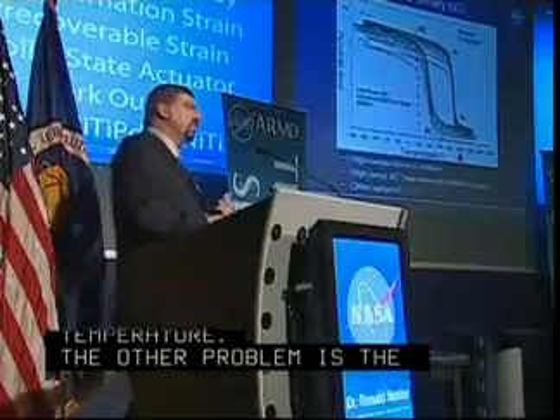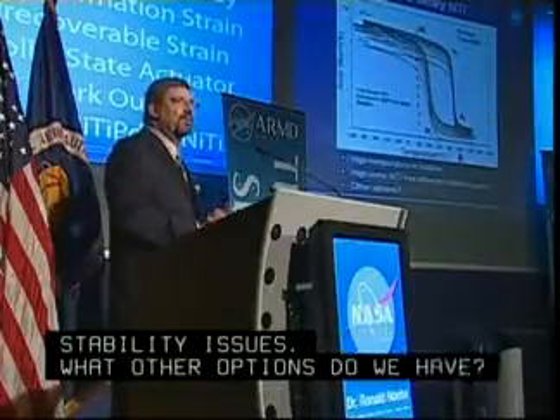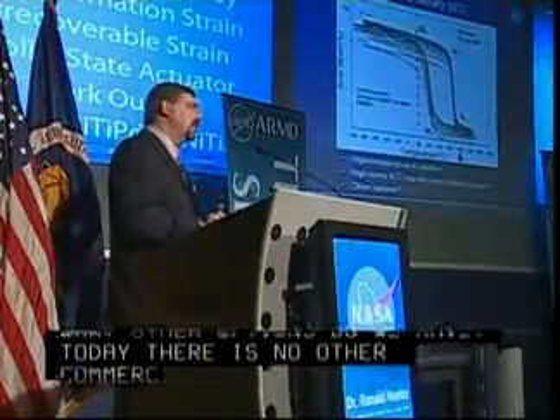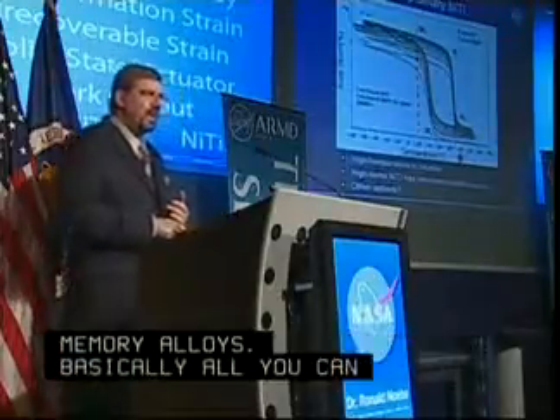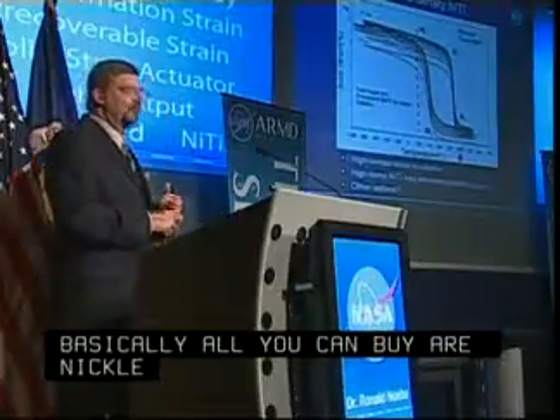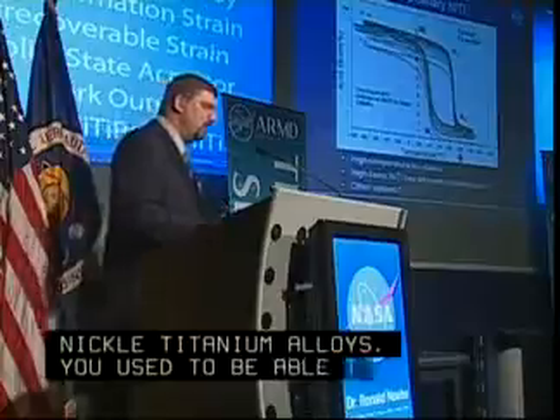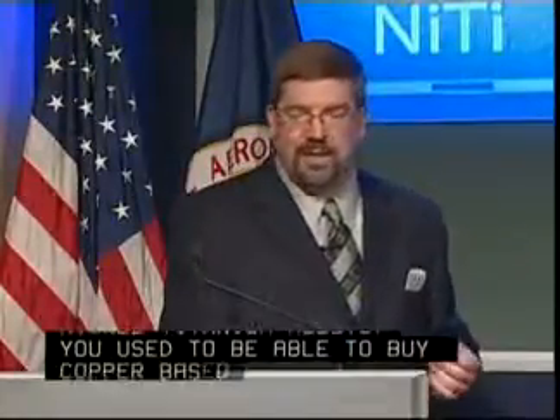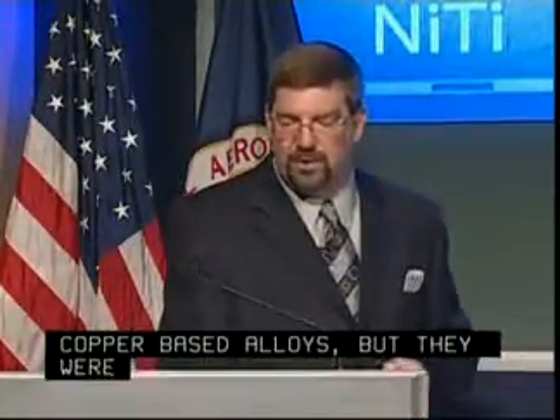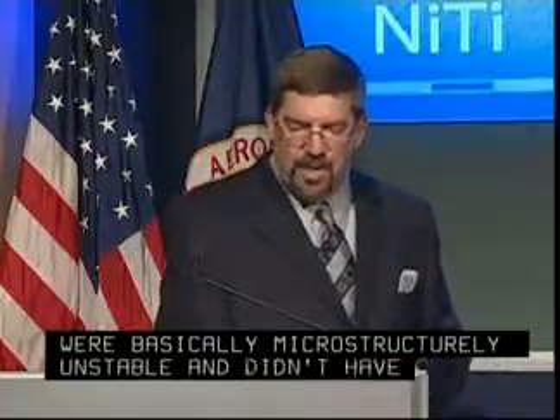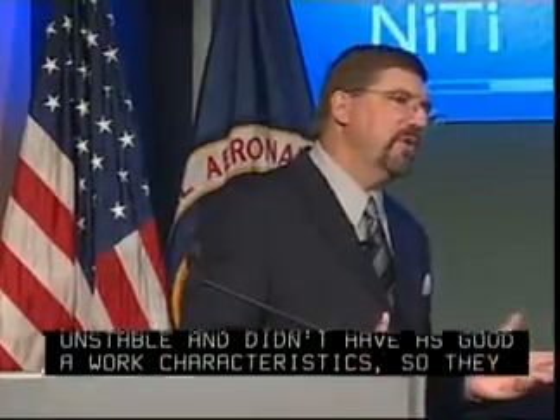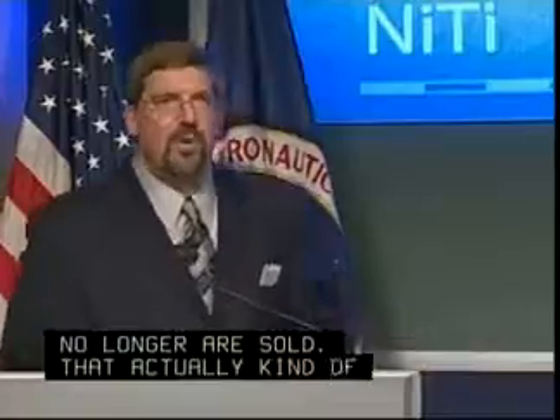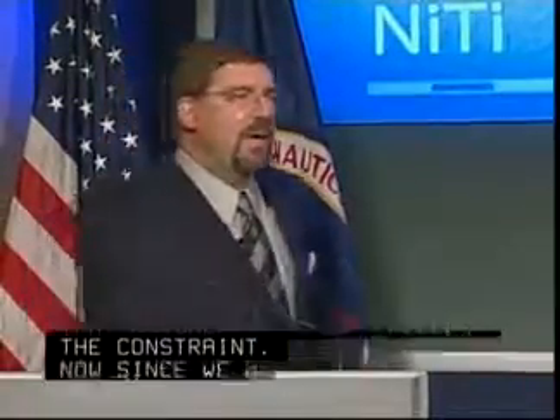Well, today there are no other commercially available shape memory alloys. Basically, all you can buy are nickel-titanium alloys. Years ago, you used to also be able to buy copper-based alloys, but they were microstructurally unstable, and they didn't have as good work characteristics, so they are no longer sold. So that actually kind of frees us of constraints. Since we have nothing else available to us, what can we do? We'll go to the lab and make our own alloy.